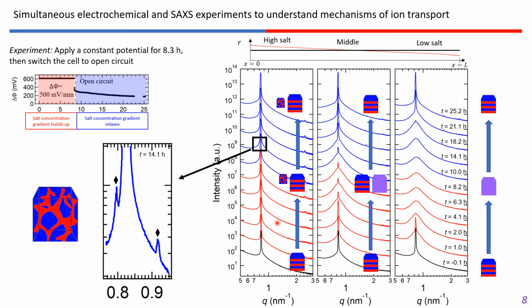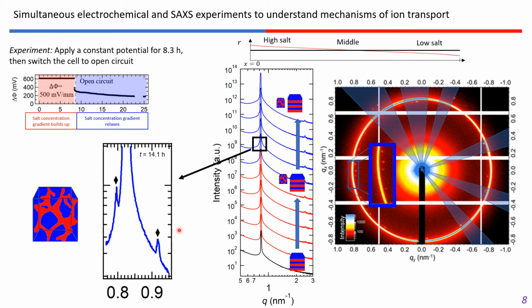However, we also observe the formation of these scattering peaks on either side of the primary lamellar peak. And if we zoom in on these and index the peaks, they're unambiguously assigned to the gyroid morphology. And if we look at the 2D scattering image, we see these sharp spots of intensity on either side of the lamellar ring, which indicates to us that this gyroid phase forms in relatively few grains.